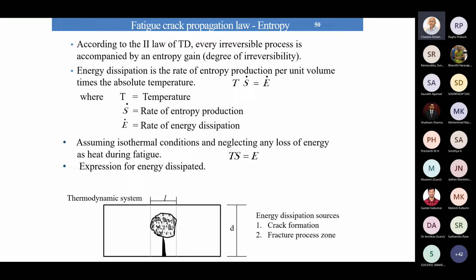So this is accompanied by a gain in entropy, and the amount of entropy gain depends upon the degree of irreversibility. So the energy dissipation can be related to the entropy gain through this relationship, where T is the temperature, S is the rate of entropy, and E is the energy dissipation rate. Now the thermodynamic system which we have considered is the 3-point bend beam with the fracture process zone with a crack. So this is a thermodynamic system.